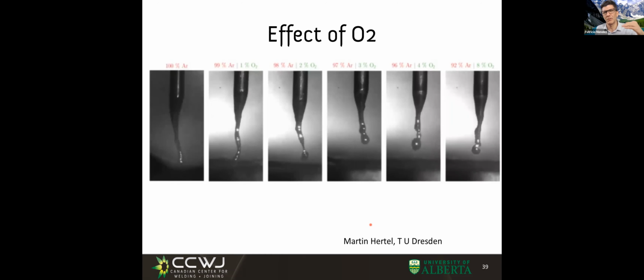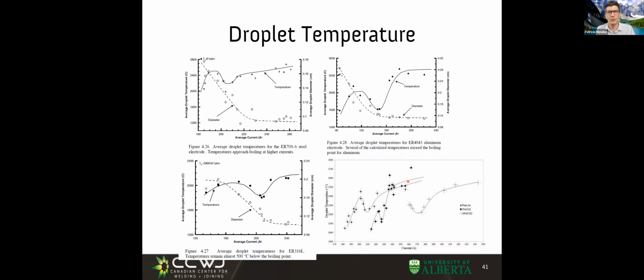And guess what? Yes, when you measure it carefully, you see it. It's quite amazing. So most of the commercial brochures say nothing about this. When you see curves of deposition rate that come from research, you get to see this little blip in the deposition rate as it goes through the transition current.